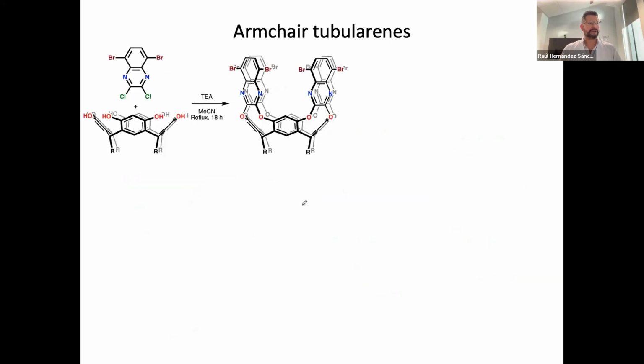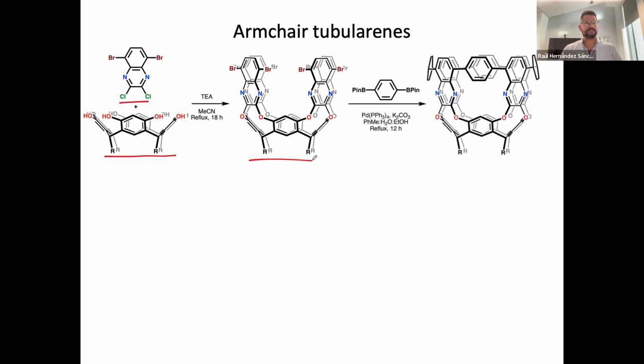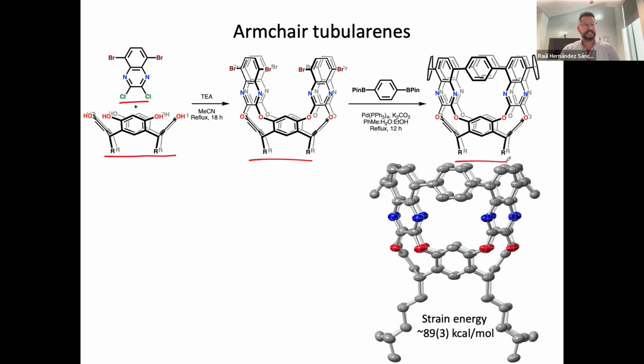So in my group, the approach that we took was to use a template shown here. You have a resorcinarene that we're derivatizing with this dichloroquinoxaline to form this compound that we call colloquially octobromo. This octobromo species, under Suzuki conditions, yields the contorted aromatic species shown here. We were able to crystallize it. That's the molecular crystal structure of that compound.